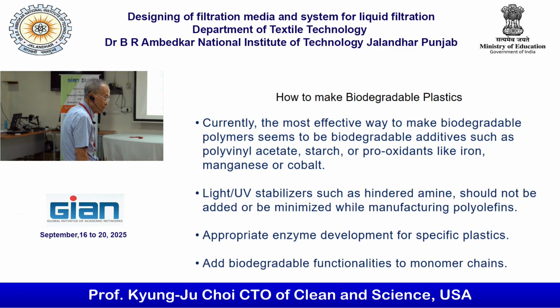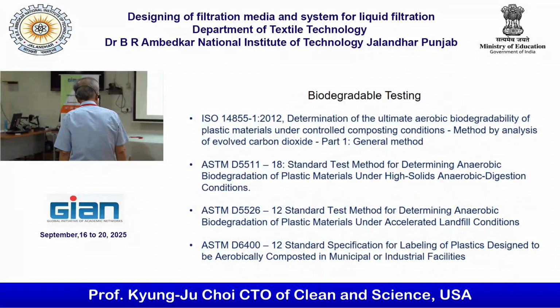The last one is not an easy one, the chemistry portion of it. So even PTFE, they can put a biodegradable branch a little bit there, and then it can be biodegradable later on. So currently, the biodegradable testing, a lot of them, ASTM is key. ISO has some. But actually, when I read about it, it's not really biodegradation of plastic material. It's kind of a short-term test. Somehow there are a lot of missing portions of it, so they have to upgrade. Okay, this is the issue.